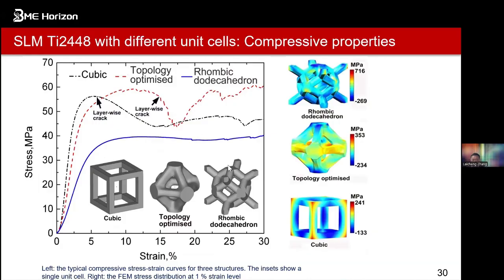That's because of the buckling for the cubic structures. It's very low density because the deformation is dominated by the buckling. So when this one does not go to the yield stress but goes to buckling, this will make it broken. But the others were deformed by this kind of structure. You can see the structure has both bending and buckling of these things. So that's why we can see the structure can do these things.